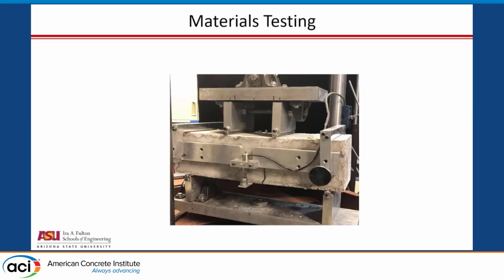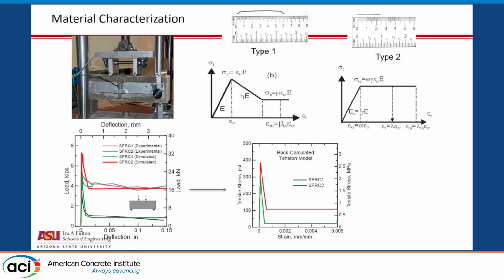We conducted the tests based on ASTM C1609, and that test allows us to do several things. One of them is to calculate the load deflection results to see what residual strength we get. The 2 fiber systems clearly show the different responses with higher fiber and lower fiber. When you plot them, what you see is this residual strength, and that's what we are banking on. In other words, my service load level should not be higher than this, even if I go for a fatigue. If I develop an S-N curve for these samples, I should always be above this. I should always be able to have this level of performance for the minimum load that's applied to it.